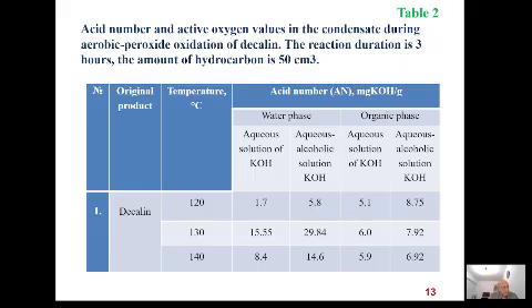During the reaction, the sequence of formation of oxidation products was traced, and it was found that maximum formation of carboxylic acid at a fixed reaction time falls at 130 degrees Celsius. The acid number determination was made twice, using an aqueous solution of potassium hydroxide and using an aqueous alcoholic solution. The latter possesses more capacity to dissolve the oxidation products, and therefore it gives higher values of acid number.